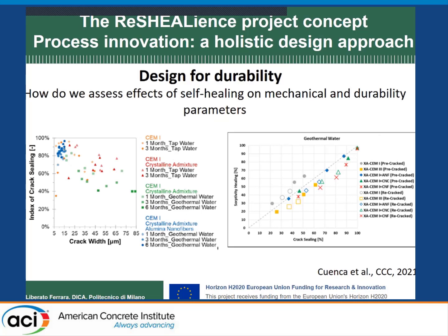An interesting thing is when we use the nanoparticles; here are some results with the crystalline admixtures and the alumina nanofibers. You can see these blue dots on the left graph, they are really in the region of very narrow crack width. So the alumina nanofibers were able to interact with the microfiber reinforcement in a synergy to keep the crack width very, very low, around 10 microns, and to guarantee the best self-healing capacity. And there is also a comparison on curing the specimens and sealing the specimens under geothermal water. You can see that these blue, red and green dots, which are the experimental data referring to the nanoparticles, are better than the gray one, which is the reference.